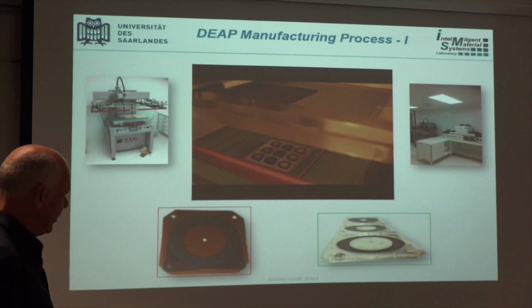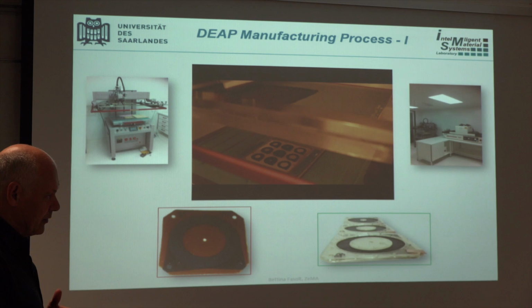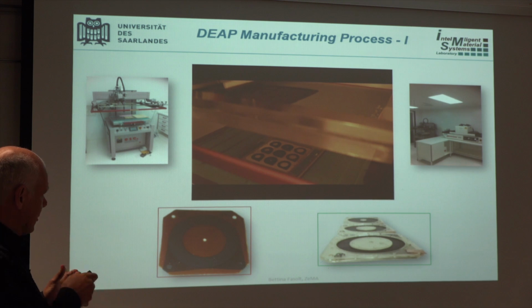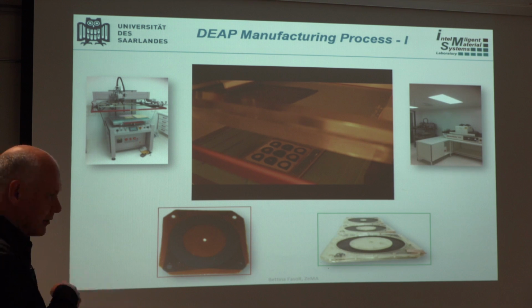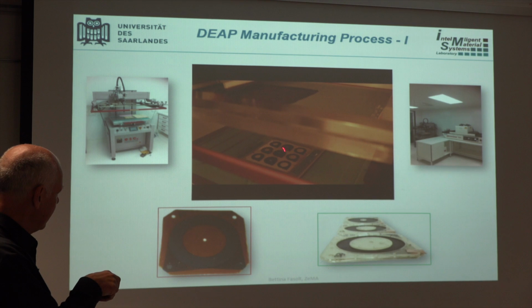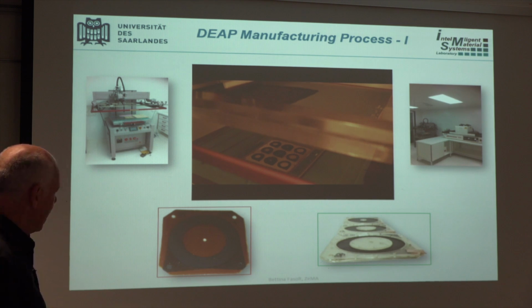So depending on your application, you basically prepare the screens with a proper geometry, and then you can print whatever is suitable on one side. You put it in the oven, cure it, then flip it around, print it again on the other side, put it in the oven again, cure it, and then you've got electrodes on a silicone membrane.